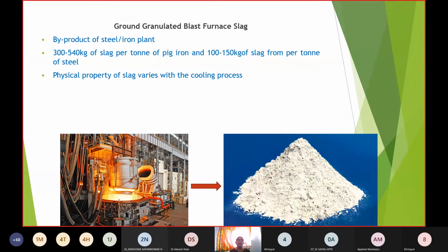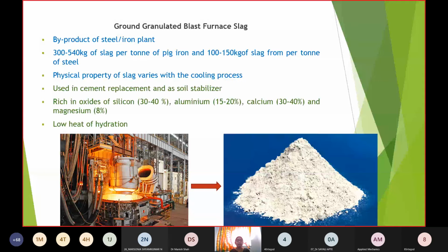So whichever slag is created, it has its own properties and its own application, which can be used for multiple activities. We have studied in civil engineering materials that you can create different forms of cement using slag. We have Portland slag cement and Portland pozzolanic cement, where slag is a good substitute. And one special aspect of slag is its low heat of hydration. This low heat of hydration suits cement, which otherwise has very high heat of hydration. So where there is a possibility of reducing the heat of hydration to control the unwanted moisture migration that leads to the cracking of soil, I can use this slag as a replacement with a suitable activator, so that it can enhance its properties and perform well as a cementitious material.